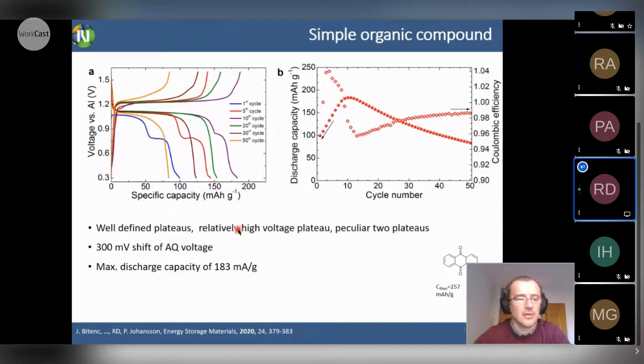Here, actually, we have connected an aluminum electrode with an organic cathode, and we have observed in the first cycle that we actually have a formation of 2 plateaus, and that was not clear why. We have this then also in the 5th cycle, then in the 10th cycle, but then in the 20th cycle this lower